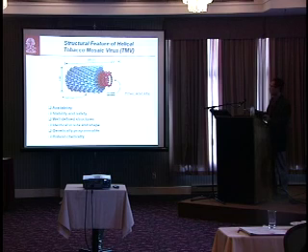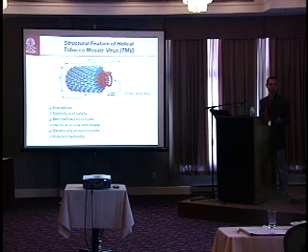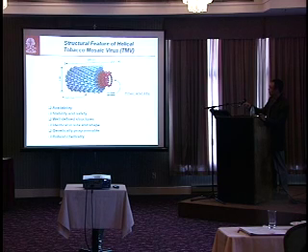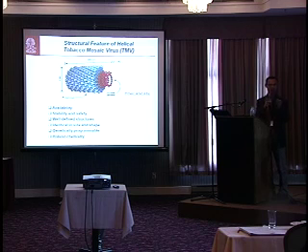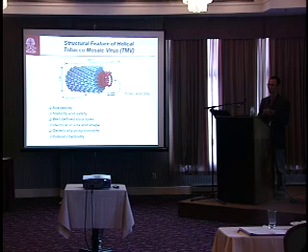The same thing as the rod-like particle I show here is the tobacco mosaic virus. It's one of the earliest viruses ever discovered. For such a particle, the length is 300 nanometers and the diameter is 18 nanometers. So for every given particle, if it's TMV in the same plants, they have the same size and the same shape. So that's another thing where I think we can win the competition: when we talk about monodispersity, what we have here is really monodispersed. They're all identical to each other.